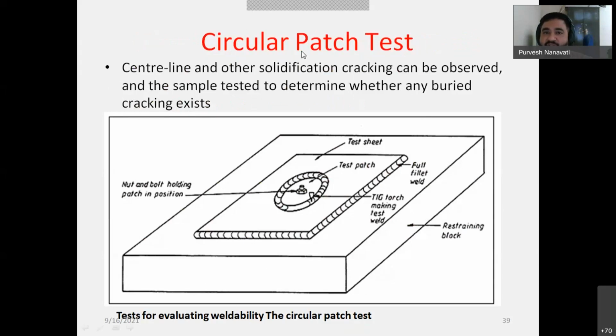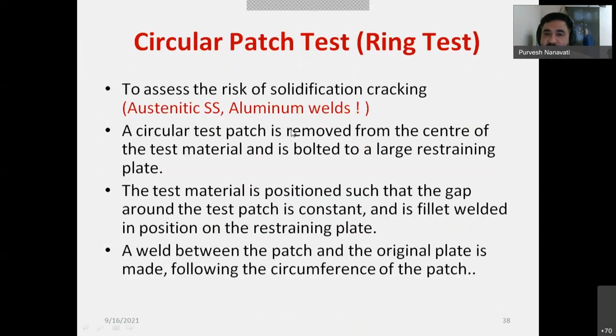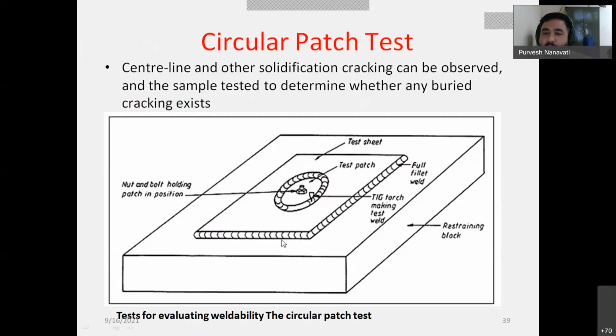This is another test, the circular patch test. It is meant for austenitic stainless steel and aluminum welds most of the time, and it is done in industry as an industrial practice. What they do, people may start with a block of say 1 inch, 1.5 inch or 2 inch thickness. Now there will be a test sheet. This is a test sheet. The test sheet will be fully fillet welded with the base plate, and there will be a hole through which a bolt will be passed, and the nut will be fitted on it to induce some restraint, and surrounding it, a weld will be performed.